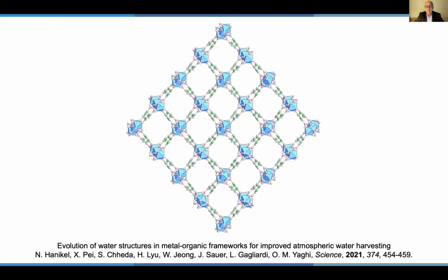Another student was successful in, let's say, figuring out exactly where each water molecule resides in the structure. The reason this is important is that if we know where the water molecules reside, we can then go in and surgically modify those adsorptive sites to control how much water can go in and at what temperature we can remove that water and harvest it, so that we can aim more and more with our colleagues at GE at